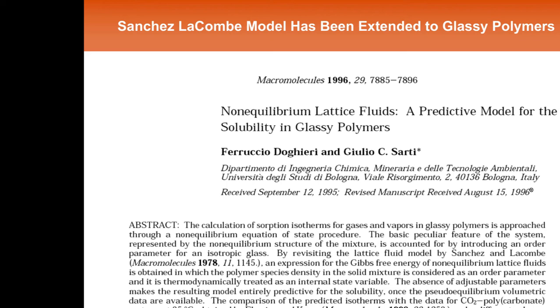How does the CH'A and CH'B compare to each other? So these capacity parameters, if you remember the units on them, they're cc's of gas at standard temperature and pressure per cc of polymer. And so the cc's of gas at STP is another way of writing moles. And so these Langmuir capacity parameters, in the simplest case, will simply scale with the size of the molecule.